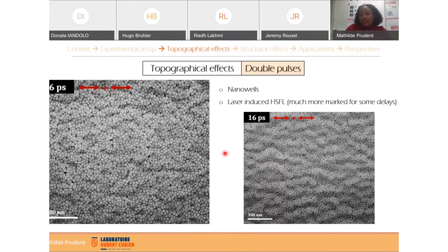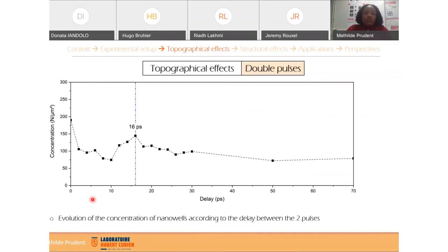These time delays match also with another characteristic. In fact, here we can see the evolution of the concentration of nanowells according to the time delay between the two pulses. And we can see that the highest concentration per micrometer square is for zero picoseconds between the two pulses. But except this time delay, we have the higher concentration of nanowells for 16 picoseconds. So it seems that the concentration of nanowells matches perfectly with the appearance of HSFL.